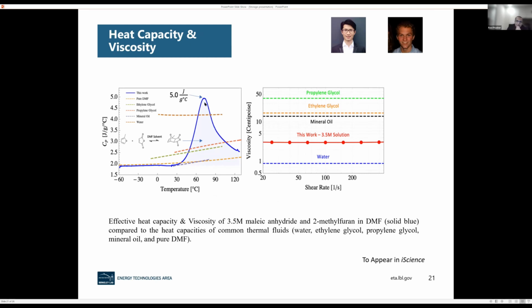As you can see, the heat capacity for limited temperature is also higher than water itself. It is definitely much, much higher than other liquids. And also the viscosity is much better than other liquids and only 3 times higher than that of water, right? So this is very good.